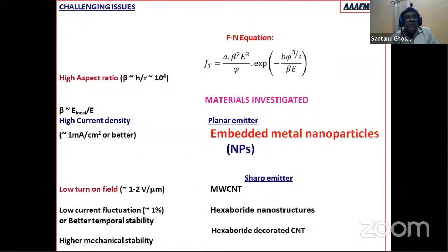But there are certain challenges for material scientists: what is required is that the aspect ratio should be high, there should be high current density, and turn-on field should be low. So several materials we have investigated, out of which is this embedded metal nanoparticle system, which I am going to talk about here. And this is a typical mathematical equation given by Fowler and Nordheim, and the field emission process depends on a quantity phi, which is the work function, and the field enhancement factor beta.